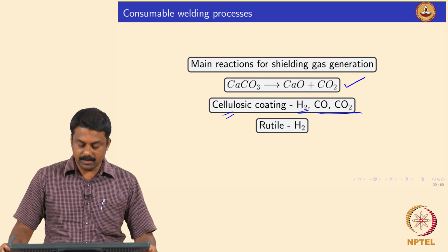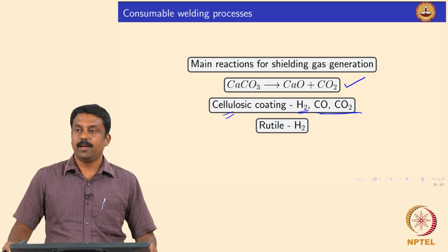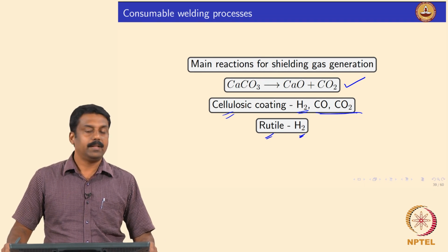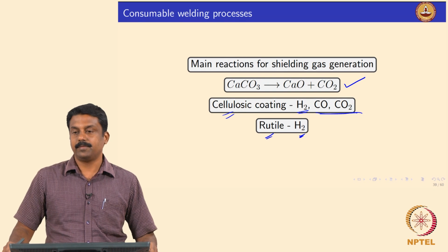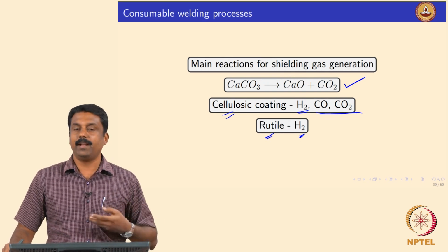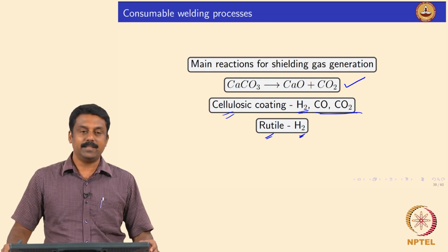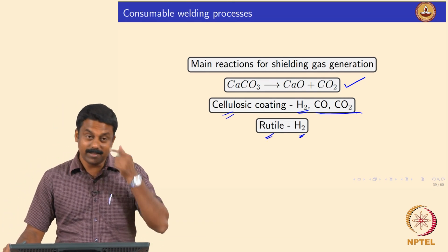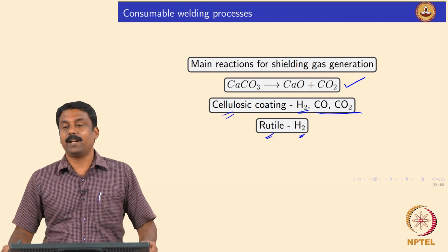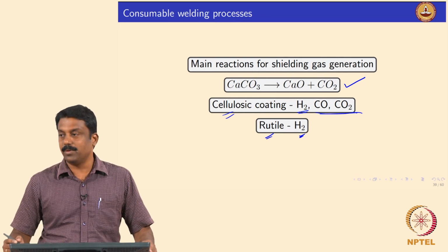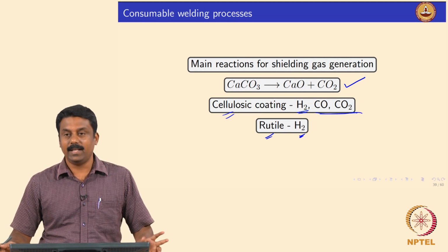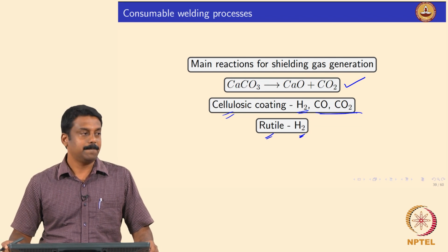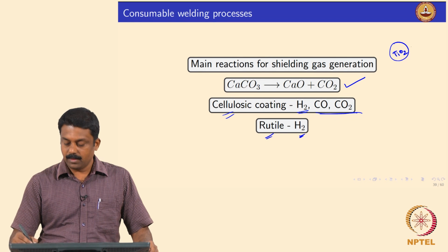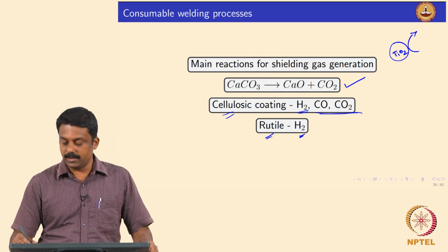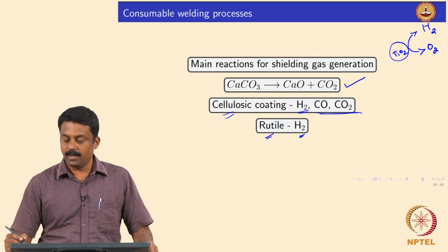Okay. So, rutile material, they contain titanium oxide, it also generates hydrogen. In rutile based fluxes, the main shielding gas is hydrogen, because titanium oxide can effectively reduce the water into hydrogen and oxygen in the flux. Okay. So, that is why the titanium oxide nowadays is very commonly explored by the nano guys to generate hydrogen by photocatalytic. So, nano titanium oxide rutile is used as a catalyst to decompose water into hydrogen and oxygen, because titanium oxide has a photocatalytic effect. So, when the water droplet comes to the surface of the titanium oxide, it promotes the disintegration of water into hydrogen and oxygen.